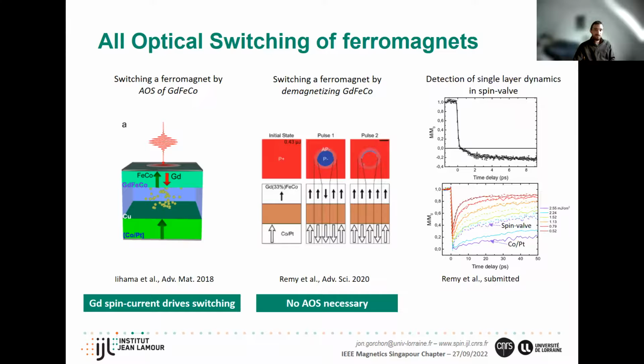And we were recently able to look at the dynamics of this process, and we saw that it was extremely fast. So it's happening in a few hundred femtoseconds. So here we're probing the dynamics only of the cobalt platinum layer. So we're doing this optical technique to separate dynamics from top and bottom layers. And another thing that we were able to look at is the dynamics in the structure versus a single cobalt platinum layer. And you can see that the dynamics are pretty different at long time scales. The cobalt platinum layer, if you heat it up, it stays hot for a long time, but in the spin valve, it cools down much quicker.